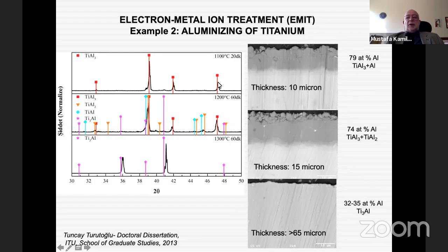So we started with a rather low temperature, 1100 degrees, and we processed our samples for 20 minutes under these conditions. And here we see a double layer structure: the titanium aluminum 3 plus aluminum layer. That shows us that there is an aluminum deposition taking place on top of the coating, a process that limits the diffusion process. Then we increased the temperature to 1200 degrees. Interestingly, the coating thickness didn't increase much. It's limited to 15 microns. And in this case, we obtain titanium aluminum 3 and titanium aluminum 2 compounds.